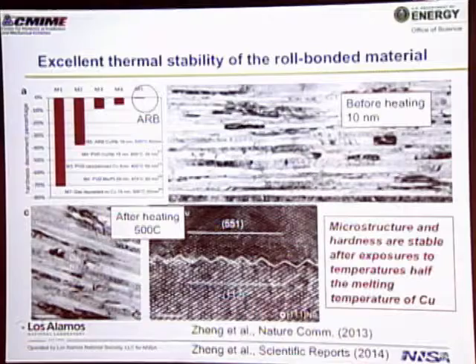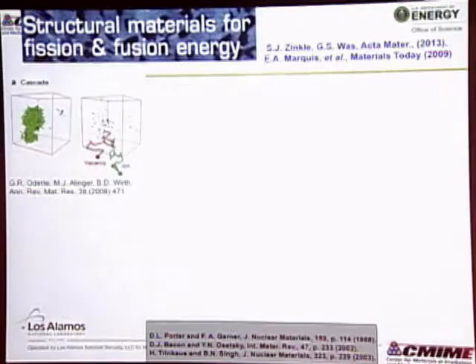So after we've heated it, we can measure hardness. This is how much your hardness goes down as a function of doing the heat treatment. This is our roll bonded material. It barely changes at all. This is if we do this to the vapor deposited material. It's not quite as stable. If you do that to a host of other nanomaterials, it won't retain its hardness. So that's good for nuclear reactors.